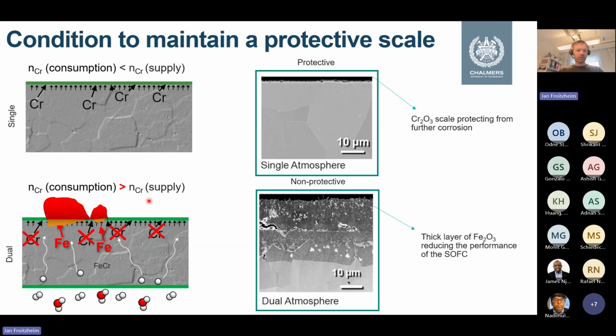However, if the consumption gets larger than the supply, we deplete our chromia scale in chromium and we start to incorporate iron, and then we get this fast-growing breakaway morphology that looks like this. So generally speaking, hydrogen is somehow affecting this equilibrium here between consumption and supply. Figuring out what is exactly going on is still partly an ongoing problem. I'll come back to that.